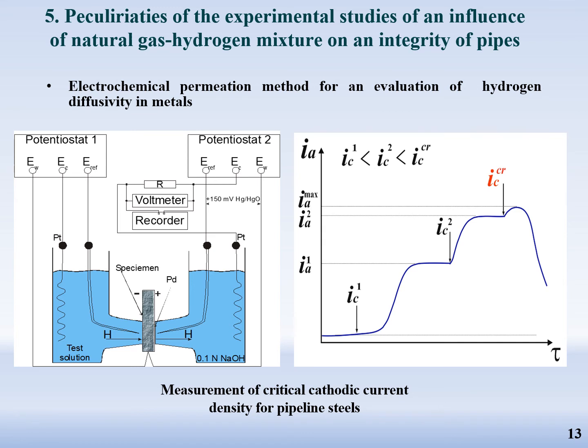The known method of hydrogen permeation should be especially useful in our case, since this method allows us to study some important parameters caused by holding of specimens in pipe: a change in hydrogen trap intensity due to development of damaging, and a measure of so-called critical cathodic current density for pipeline steels. This parameter can serve as a parameter of the sensitivity of steel to hydrogen cracking: the lower the level of critical current, the higher the sensitivity to hydrogen cracking.